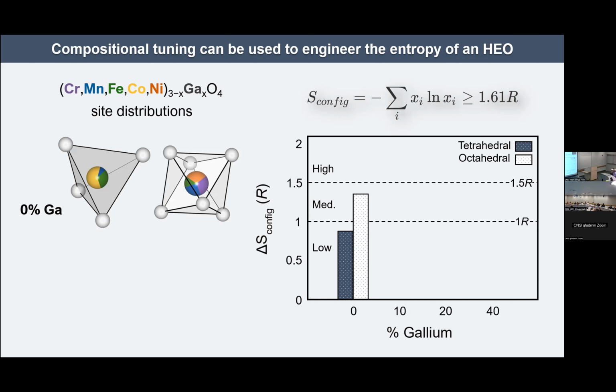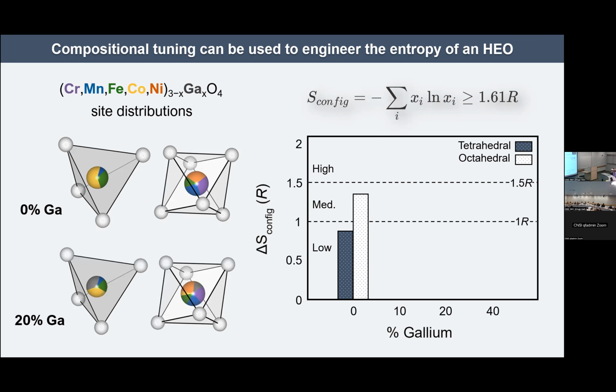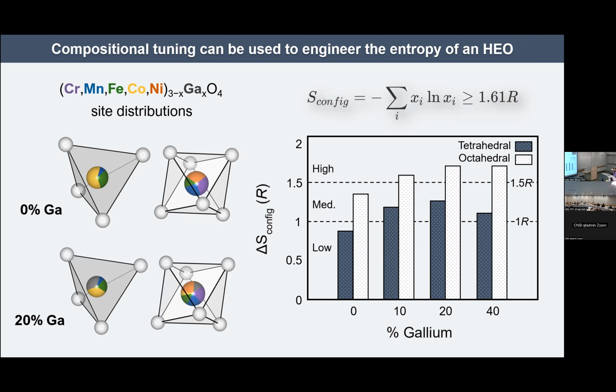And then we can look at what happens now once we have the gallium coming in. We actually don't measure gallium directly, so it's important to point out that gallium is inferred by deduction. But you can see that now on my octahedral site, in this 20% gallium system, I have representation of all 6 elements. So things are actually looking quite promising. And indeed, I pretty quickly move into the high entropy limit in these gallium substituted samples.